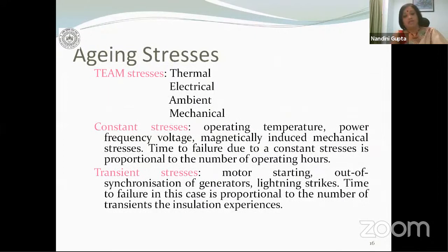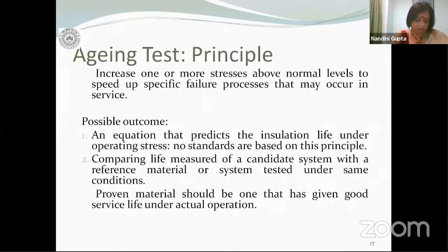Then of course, when we are looking at constant stresses, what we are interested in is that we apply a constant stress and we note the time to failure, and generally this will be proportional to the number of operating hours. So as long as you keep the machine in operation, it will drive the aging mechanisms. But apart from constant stresses, you might have transient stresses, which the insulation may be subjected to. For example, due to motor starting, out of synchronization of generators, due to lightning strikes. In this case, it doesn't really matter how long the insulation system is in service. More important is how many of these transients it can be expected to survive. So the number of strikes in that case becomes important. So we have to distinguish between constant stresses and transient stresses.